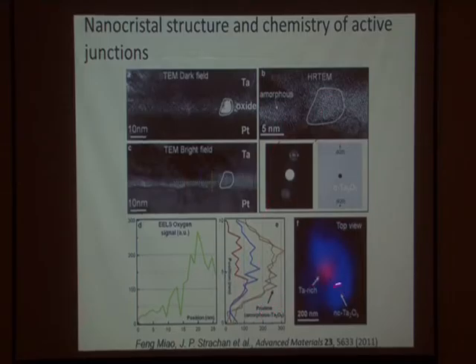Then with EELS you further validate that, and it looks like the profile of oxygen vacancies, or oxygen, is not that sharp. But when you look at the conductivity of tantalum oxide, what you find is that it grows faster than exponentially with the vacancy content. So it's really a very, very small point that is actually contributing to the conduction. I don't have that fully developed, but we have seen, and other people have seen, quantized conduction.